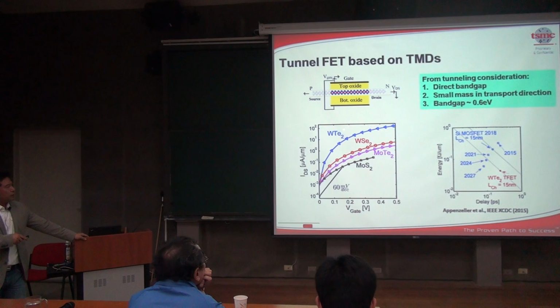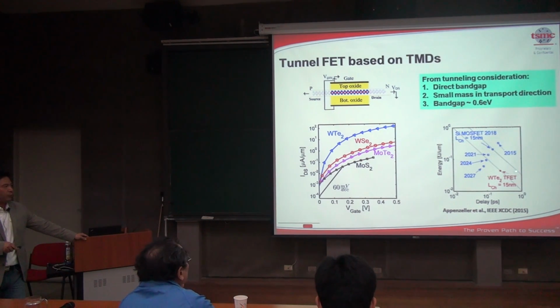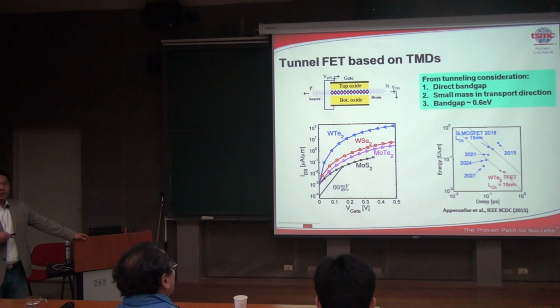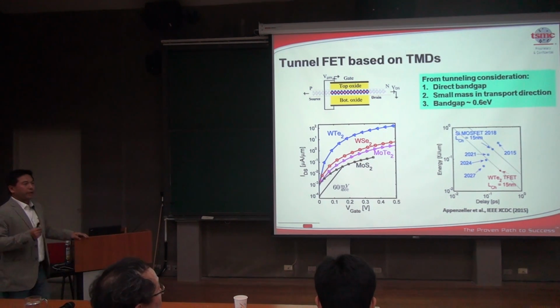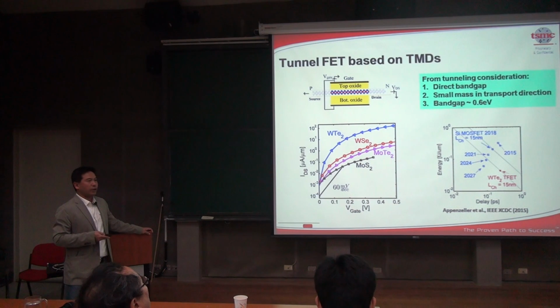Now, this was a simulation that was made for different types of 2D materials. It shows that for certain types, such as tungsten telluride, you could in principle get the best on current and have better performance than silicon devices. We'll go to this chart in more detail later. Now, the reason for tungsten telluride to be better than MoS2 is actually because of a smaller effective mass and also a band gap that's smaller than MoS2 when you use heavier materials. Because in the tunneling behavior, you want the band gap to be small and the effective mass to be small to have a higher tunneling probability.